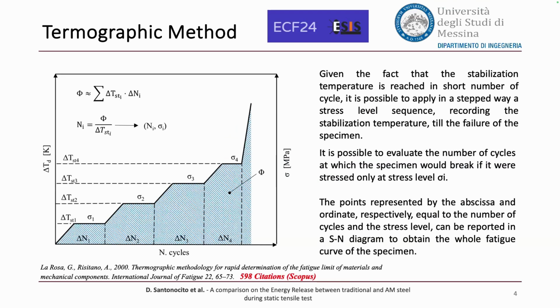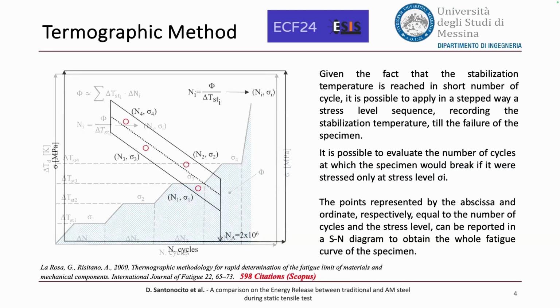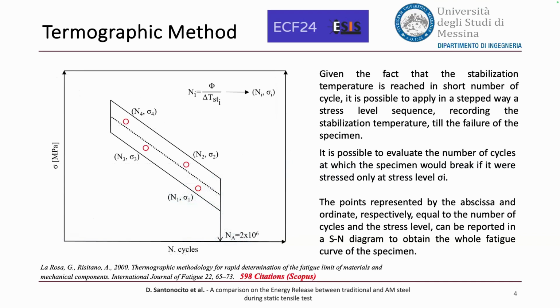So notice that the stabilization temperature is reached in a short number of cycles. So it is possible to apply in a stepped way the stress level sequence, recording the stabilization temperature for each step until the failure. In this way, it is possible to evaluate the number of cycles at which the specimen would break if it were stressed only at the stress level sigma i. And we will obtain some points that are represented by number of cycles and stress level. And in this way, we can build the Wöhler curve.